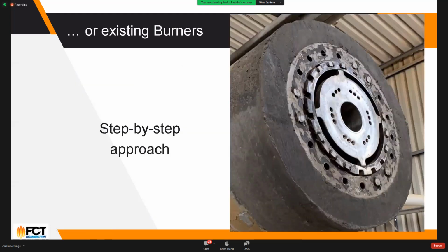So you can do this with a brand new burner, but you can also use existing burners. As you can see here, this originally was a burner from the competition, and then we wanted to change part of it. So we tapped some of the holes you have here to promote higher entrainment of secondary air, while changing the configuration of the swirl to promote even more mixing and a better flame. So this was a very successful project, very cheap to install, and finally they got the result they wanted just by changing some principles or the geometry in the burner tip.